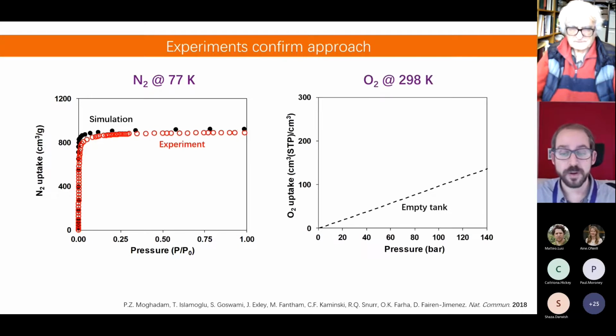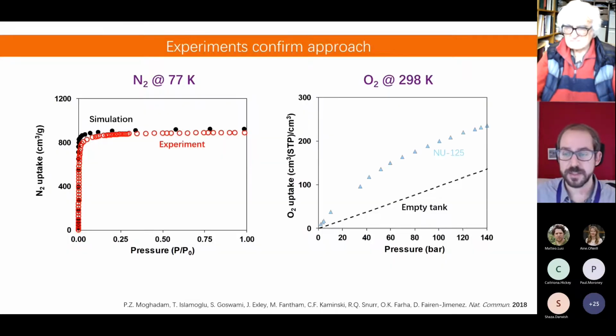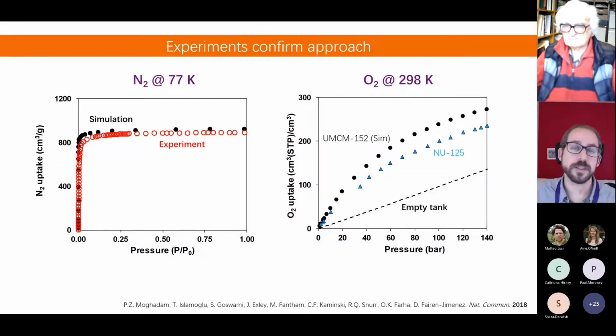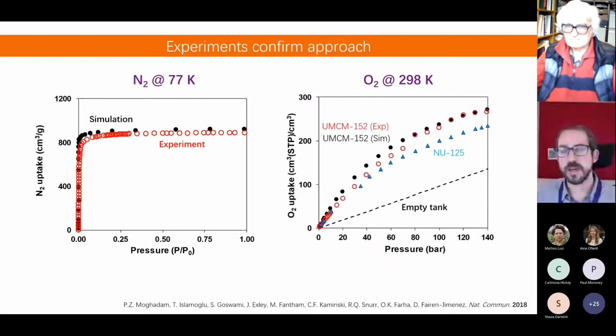If we go for the oxygen storage, the real application, this is the amount of gas stored, cubic centimeters of oxygen per cubic centimeters of metal-organic framework when we increase the pressure. This is the comparison with an empty tank. This is the effect of compressing the oxygen inside the tank. This is the best material that was published in the literature, something called NU-125. This is the best material that we identified in our screening, the simulation, and this is the best material